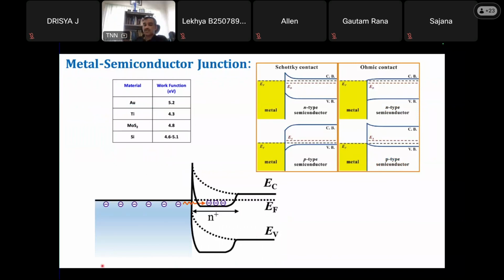Is it an issue in silicon semiconductors? Silicon semiconductor technology has already matured. It is an issue, but there are ways they address it in a bulk semiconductor. So the thumb rule for a Schottky and ohmic contact, again a textbook thing many of you might have already studied: for an n-type semiconductor, the metal should have a lower work function. For example, MoS2 is a semiconductor having a work function of 4.8. So if you use a gold contact, it will have a Schottky barrier. But if you use a titanium contact, it will have an ohmic contact. So you really need an ohmic contact here.